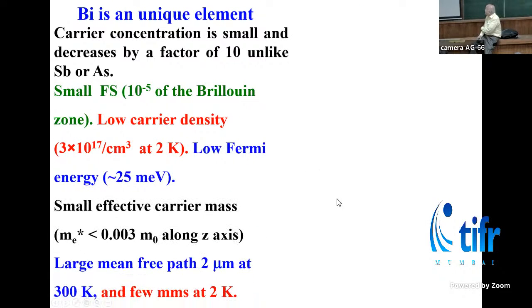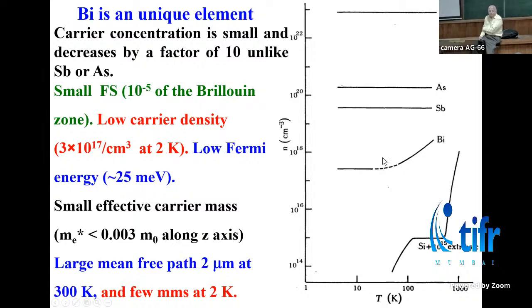So bismuth is a unique element, and it has an extremely small Fermi surface because its carrier concentration is small. It occupies just 10 ppm of the Brillouin zone, has a low carrier density, and an extremely large mean free path. It's of the order of a micron at room temperature, and it goes to several millimeters at low temperatures. So the electrons are ballistic out there. Yeah, the Fermi velocity for this is about 10 to the power of 7, something like that. I will show you that graph later. The important thing here is that the carrier density changes as a function of temperature, unlike all its cousins like antimony, and so on. This is something very unique.